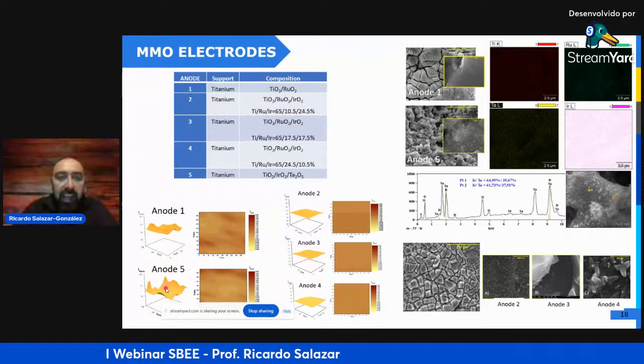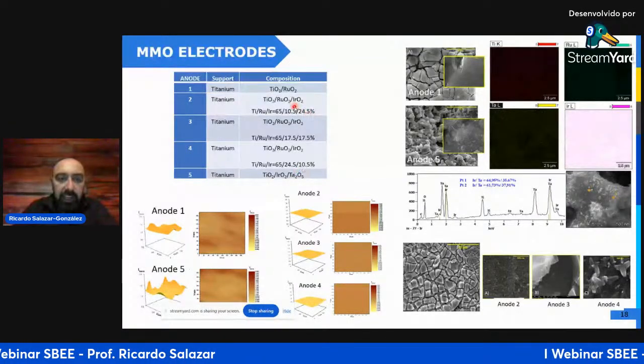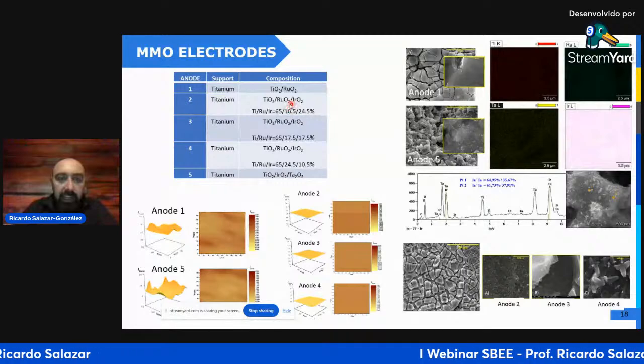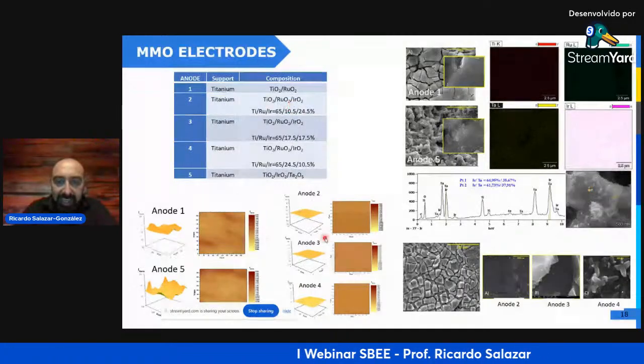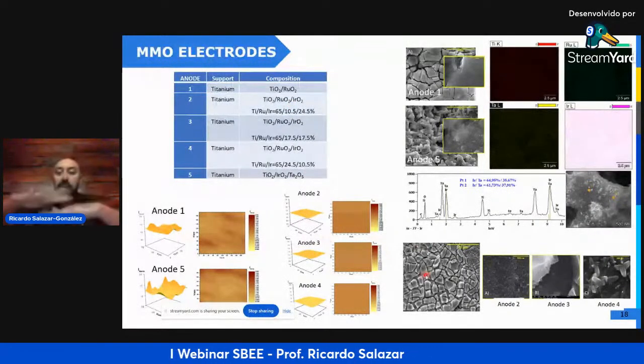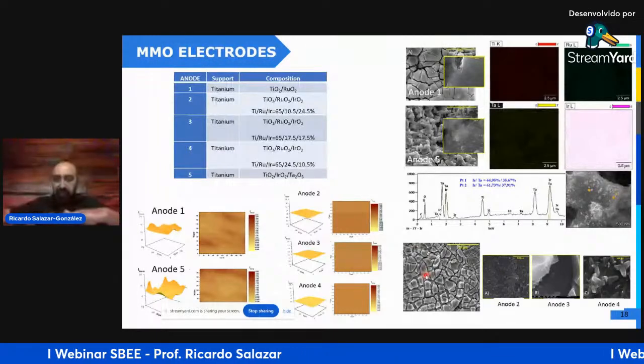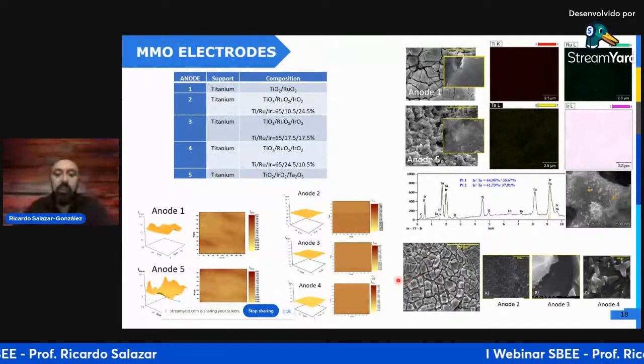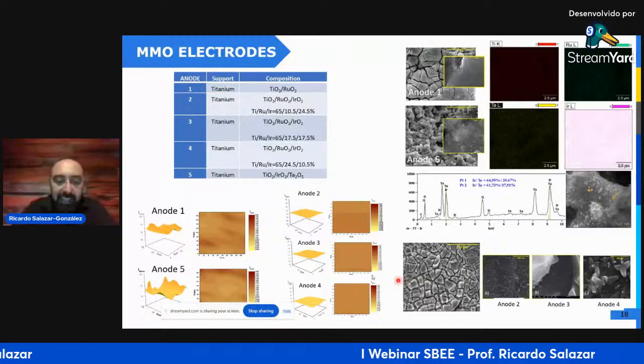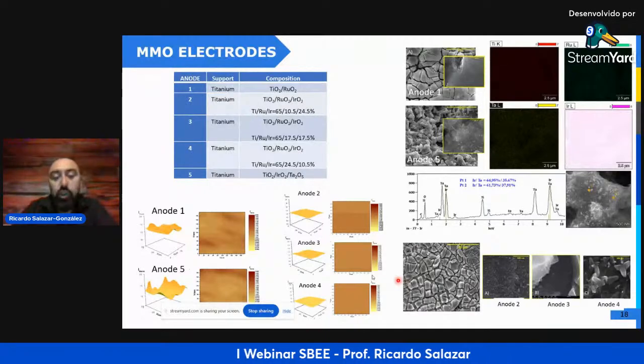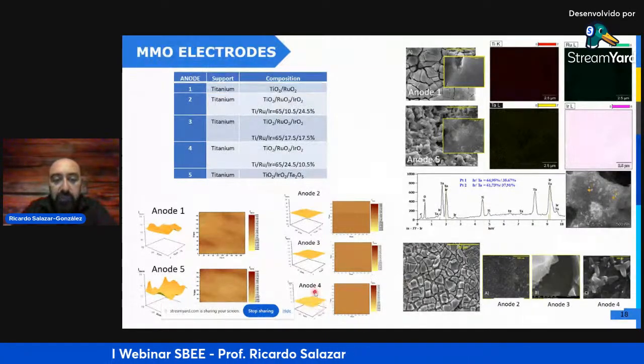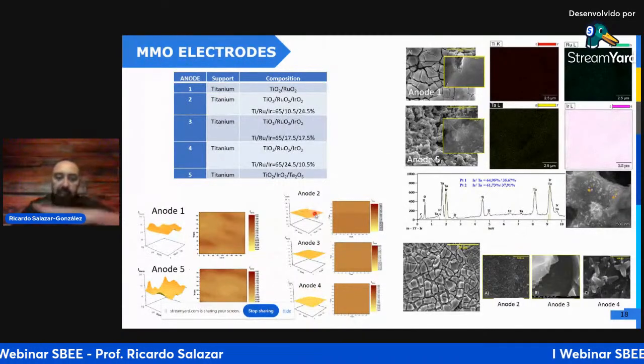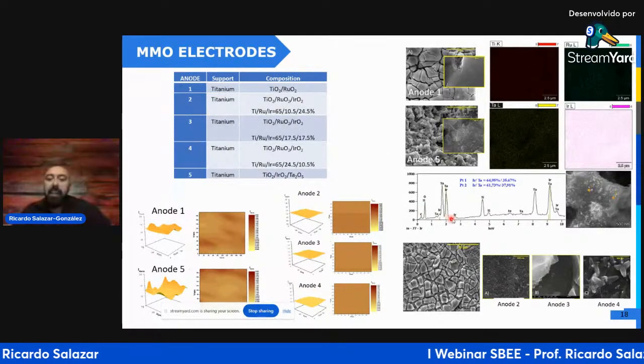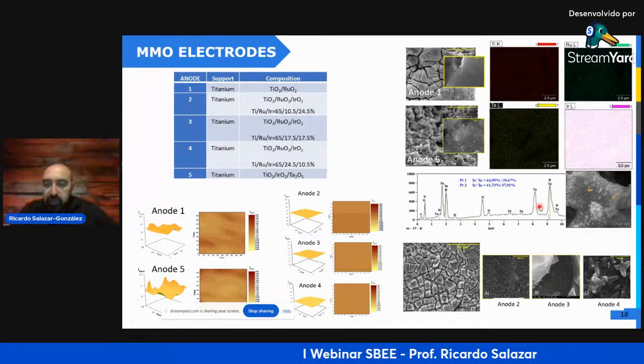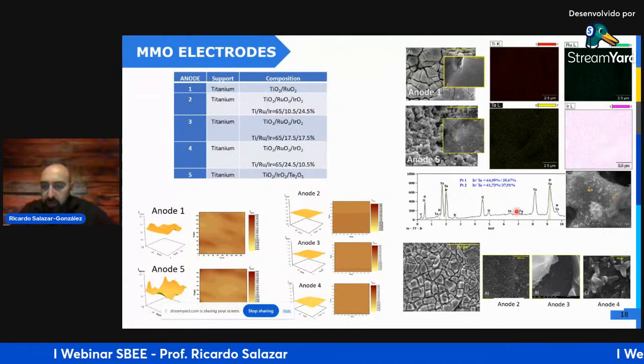But when we have a mixture of ruthenium and iridium oxide, this cracked surface is homogeneous over the whole electrode, and you can see that in this case the electrochemically active surface is very homogeneous in all of the electrode. And here you can see the presence of different oxides of tantalum, iridium, and ruthenium.